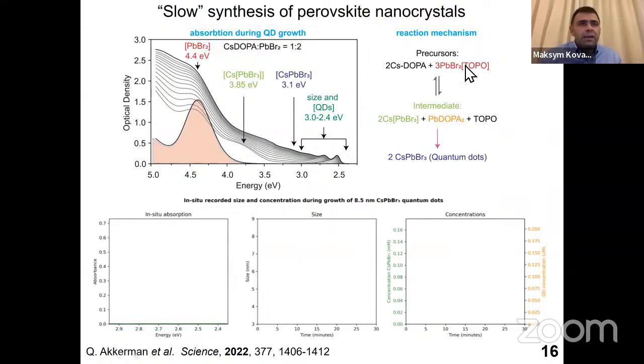So the idea here is that we avoid using any amine in the system, because when you have amine, it will become ammonium. And if you have ammonium, you will need to have a counter ion, which is lead bromide, cesium lead bromide 3 minus, lead bromide 3 single minus, which is too reactive. So you had better not have active ionic species in the solution. You should go as molecular as you can, and therefore you will have much slower nucleation and growth.